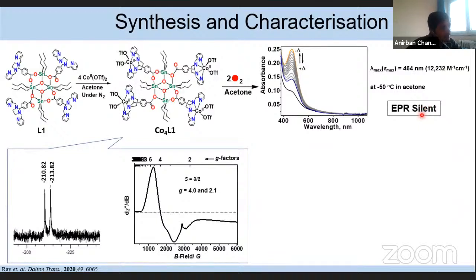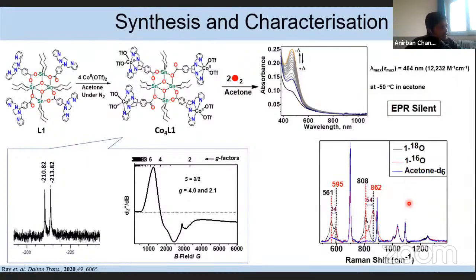The new species is EPR silent, and to characterize it more, I did the resonance Raman experiment with 16O and labeled 18O oxygen, and I found two isotopically sensitive vibration bands at 862 centimeter inverse and 595 centimeter inverse. The 862 centimeter inverse band downshifted to 808 centimeter inverse upon 18O labeling, and the other also downshifted to 561 centimeter inverse upon 18O labeling. So from the 54 centimeter inverse downshift of this band, we correlate it with the O-O vibration of a peroxo species, whereas the 34 centimeter inverse downshift of the band we correlate with the metal-oxo stretching vibration, and these two values exactly match our DFT calculated parameters.